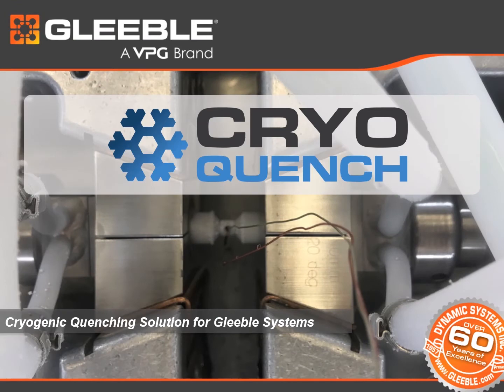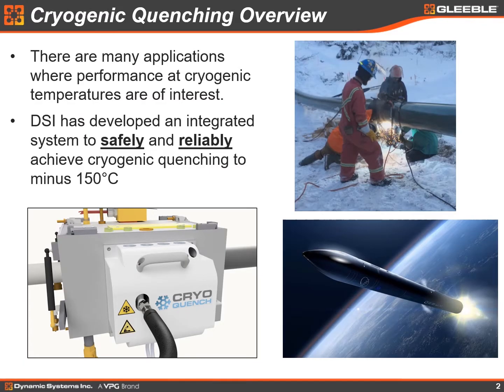Thank you, Dan. I would like to use the next 10 minutes or so to discuss our new cryogenic quench system that allows Gleeble users to do studies at temperatures down to minus 150 degrees centigrade. There are many reasons why researchers might want to study materials at these low temperatures, one of which is simply either use or fabrication in Arctic or low temperature environments, and another is cycling between extreme high and low temperatures, such as might occur in, for instance, a rocket engine on an orbiting satellite that has to fire periodically and therefore cycles between the temperatures of the rocket flame and the low temperatures of space.